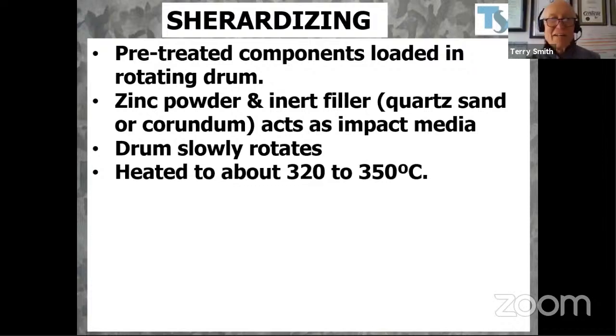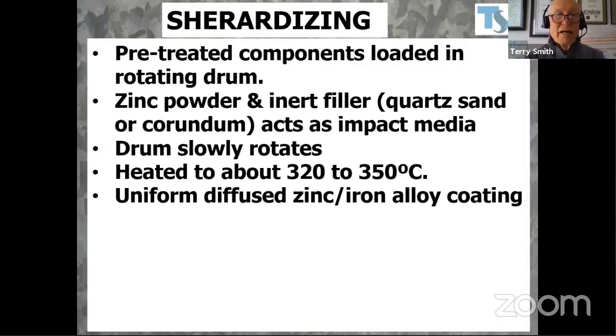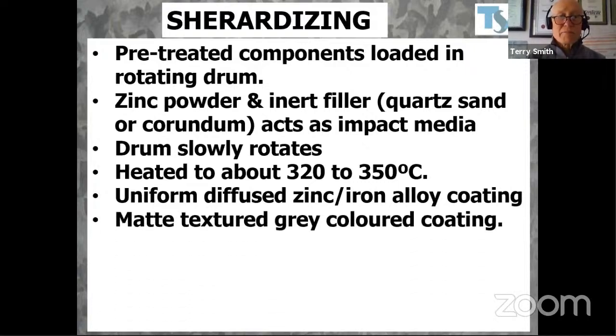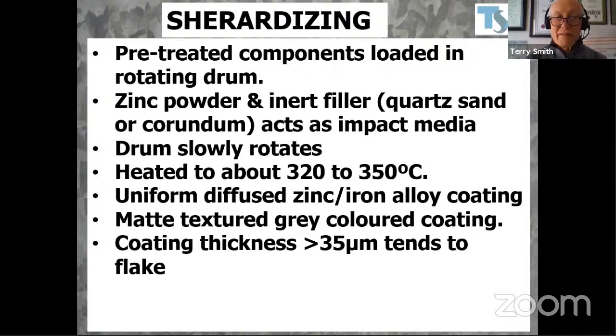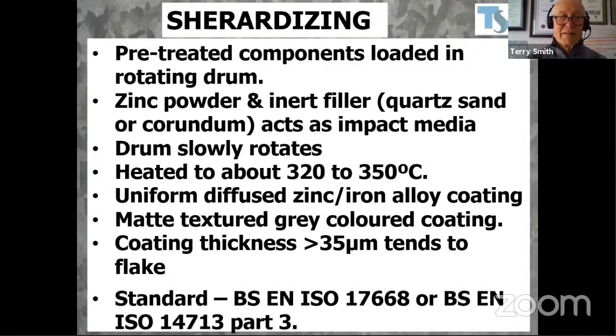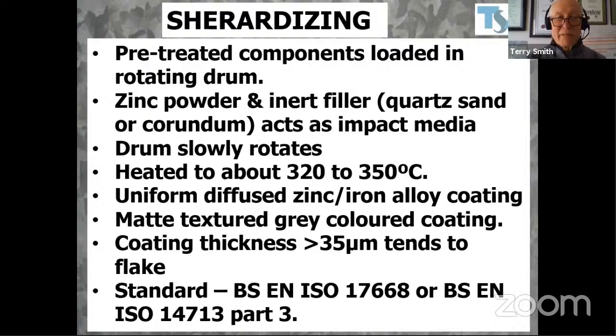There we are. The drum slowly rotates, heated. This is not room temperature, but the drum is heated, or the contents are heated to about 350 degrees C. A uniform diffused iron zinc or zinc iron alloy layer is formed. It's a matte or textured gray color coating. Coating thickness greater than 35 microns tends to flake. And there's a standard, it's BS EN ISO 17668 or BS EN ISO 14713, which is part of the galvanizing spec.